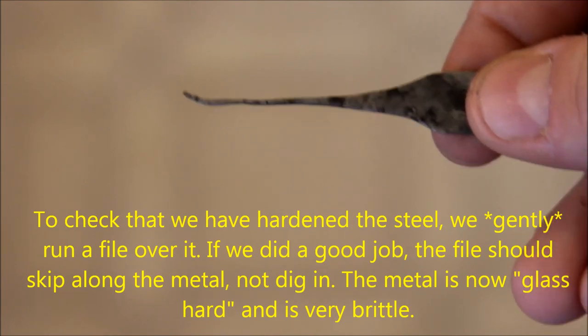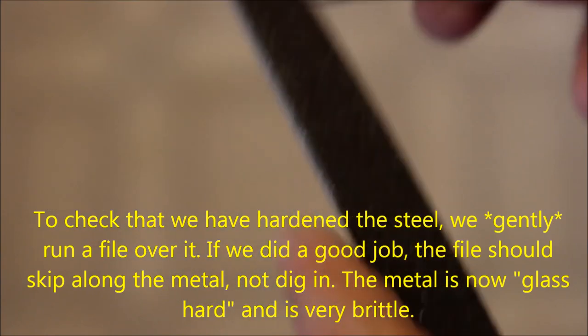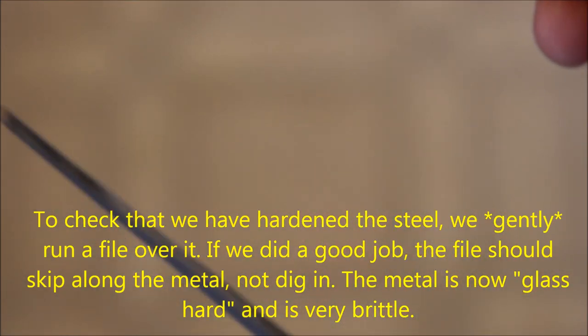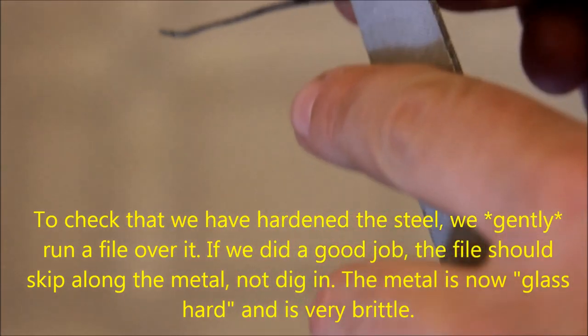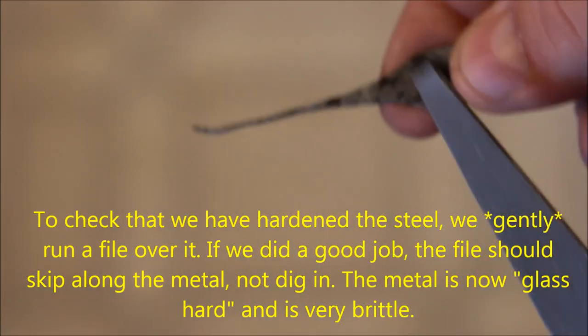Now we're going to check that the metal is hard, or what they call glass hard, by running a file along it. The file should sort of slip off of it and the teeth shouldn't grab in. If they do, that means we haven't done a good job hardening it. In this case it looks pretty good.